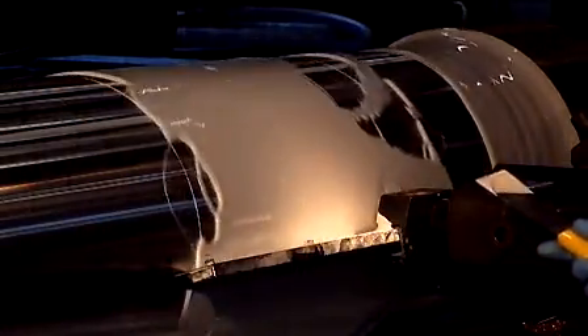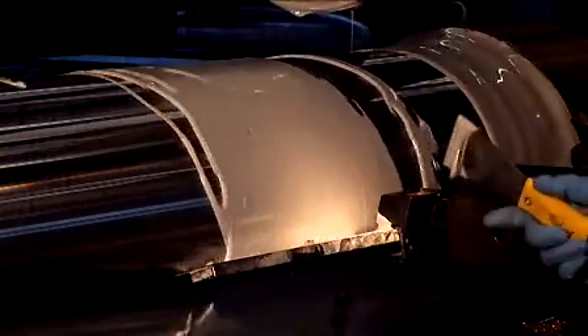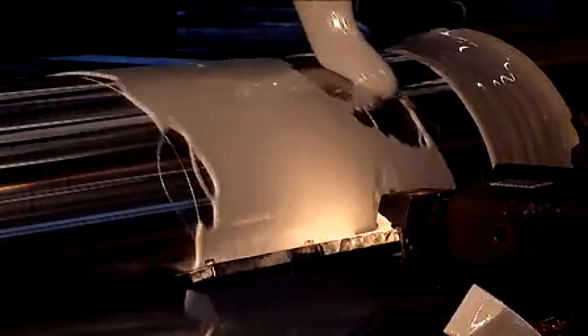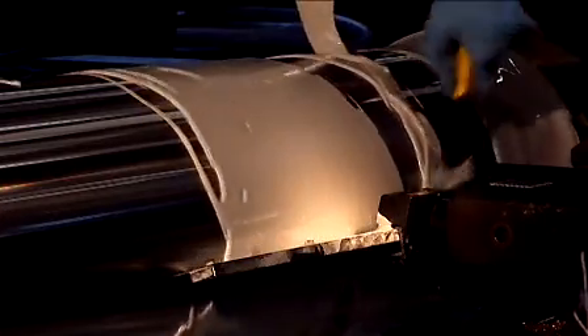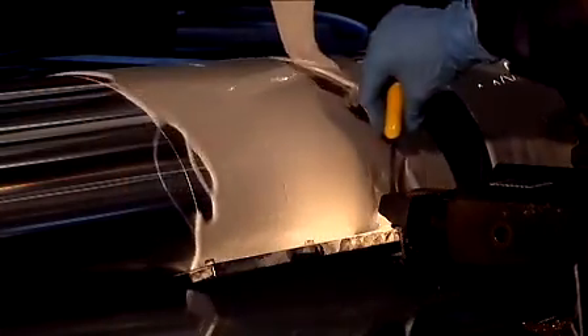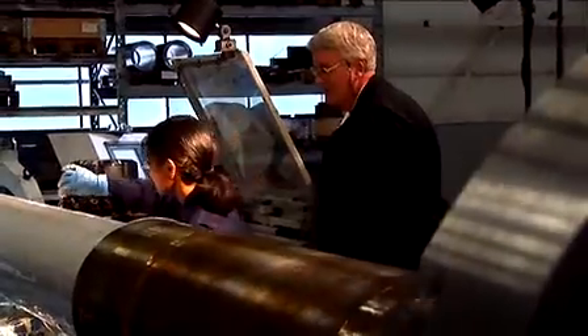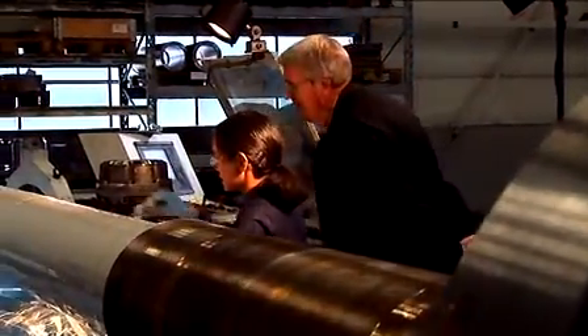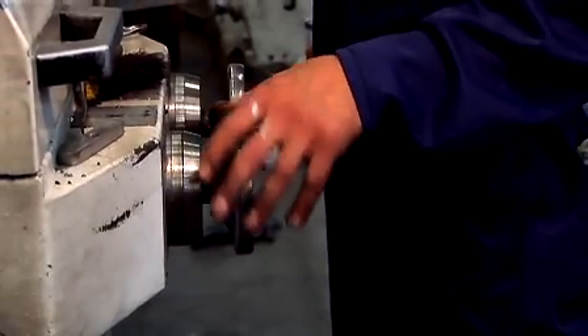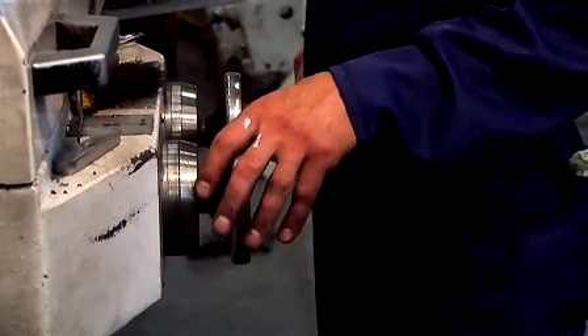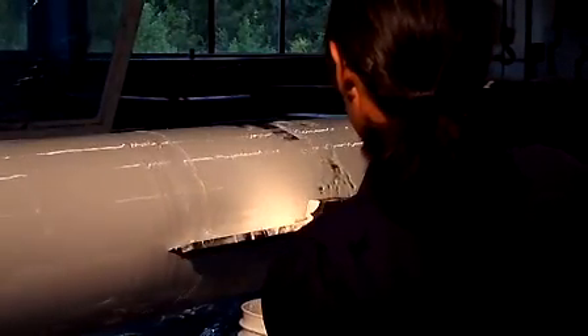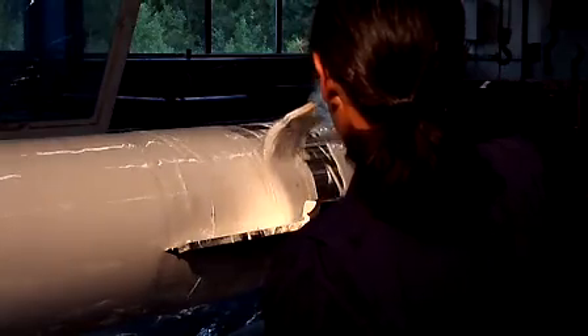Mount the doctor blade on the lathe, positioning it at 2.5 millimeters or 100 thousandths of an inch away from the shaft. Rotate the shaft on the lathe and slowly pour Thor Coat on top of the shaft in a zigzag motion. After Thor Coat has been spread evenly over the shaft, stop the lathe and quickly check for thickness accuracy using the wet film thickness gauge. If necessary, adjust the doctor blade to achieve a thickness of 2 millimeters or 80 thousandths of an inch. Continue this process until the shaft is completely coated.